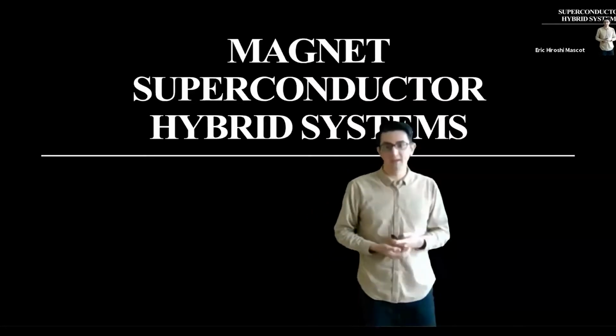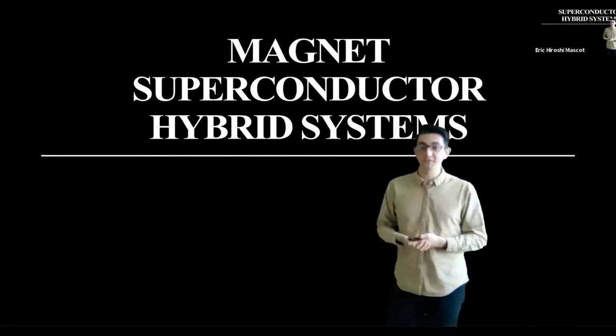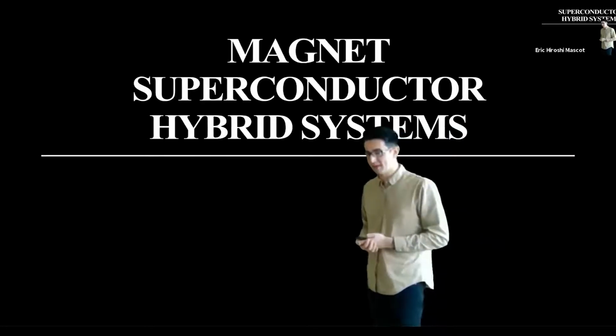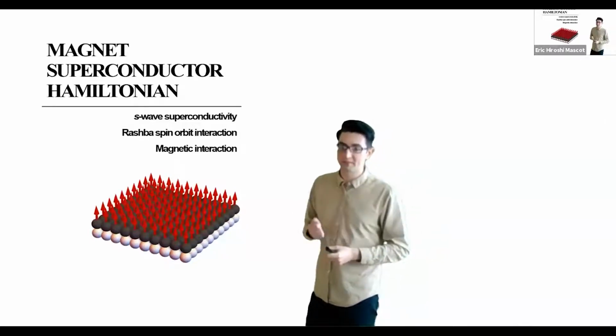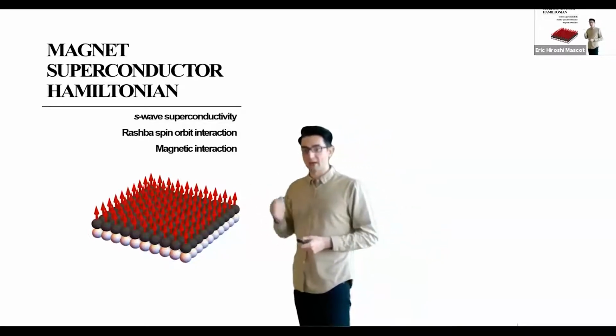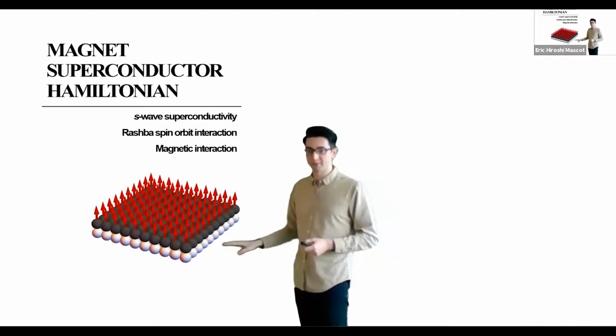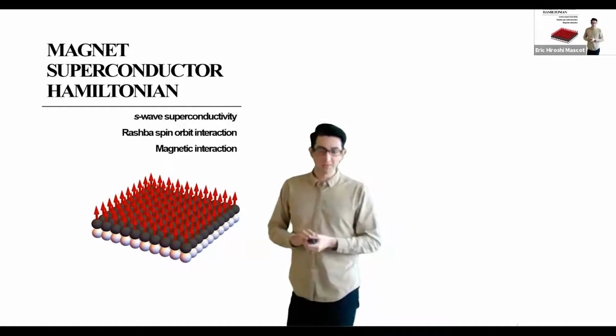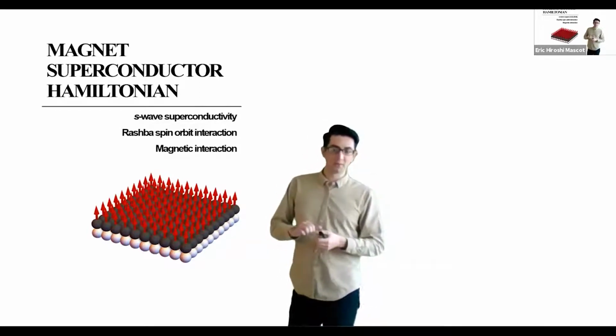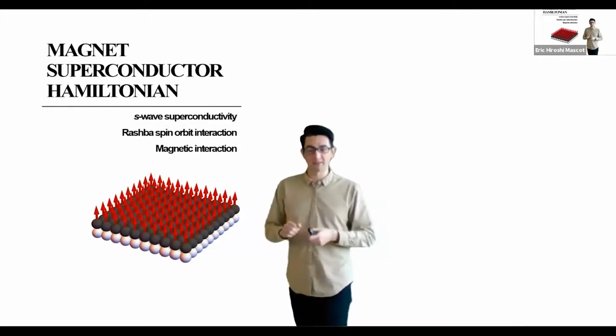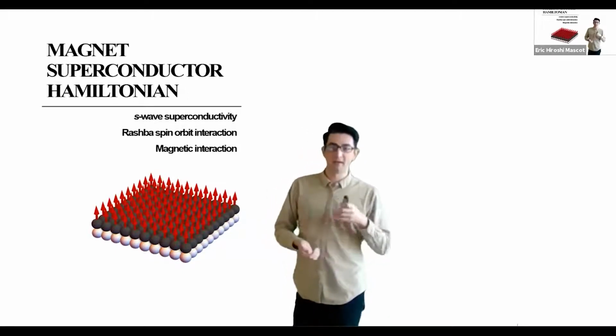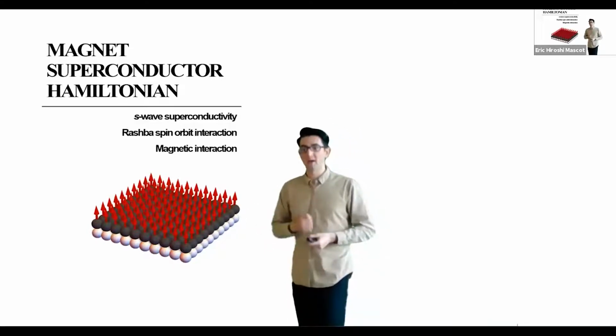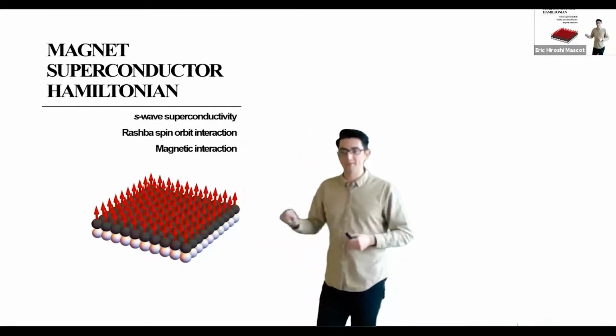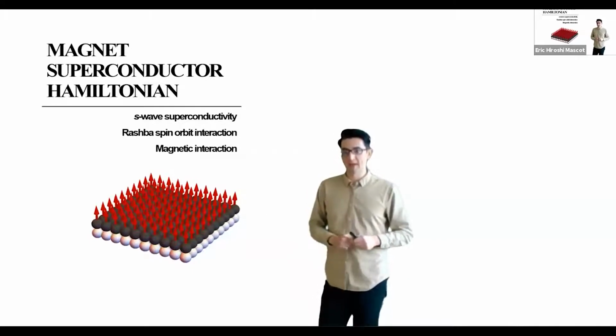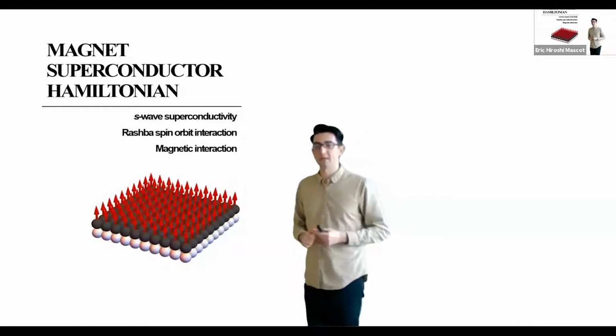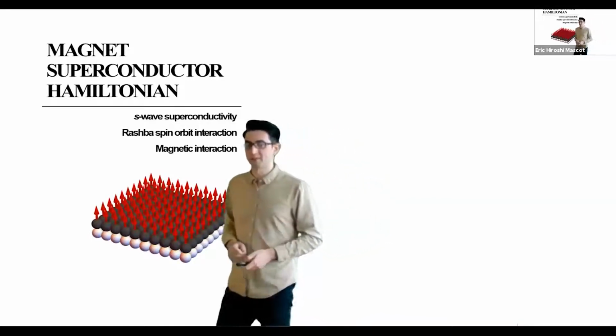So here I'll introduce the theory of the magnet superconductor hybrid system. The Hamiltonian has 3 key ingredients. We have an S-wave superconductor. The substrate is an S-wave superconductor. And on the surface, you break inversion symmetry. And so when you have broken inversion symmetry and spin-orbit interaction, that creates what's called the Rashba effect. So we add a Rashba spin-orbit interaction. And then we have these magnetic atoms on the surface. And the local magnetic moment interacts with the spin of the electrons in the substrate.